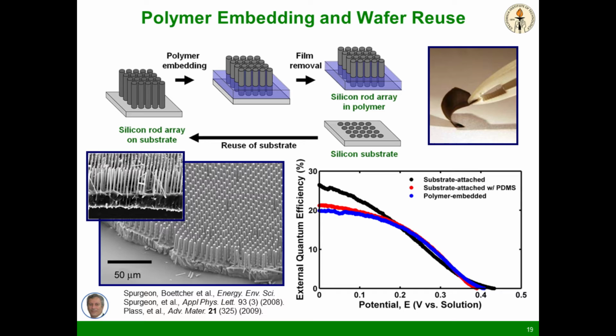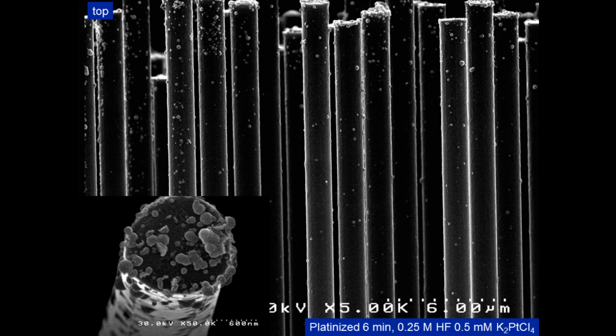Well, we need a catalyst. In our first catalyst to make water into hydrogen from silicon, we just decorated for demonstration purposes some platinum particles that you can see here onto the sidewalls of this microwire array. Now, we don't want to use platinum in the end because it's too precious and expensive, and so we've replaced it with something else that I'll tell you about later. But just to demonstrate that we're on the right track, we started there.